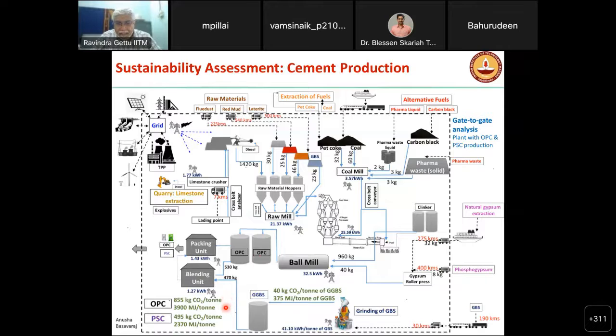It requires 3,900 megajoules per ton of cement. Now, the same cement, instead of it being OPC, was PSC, Portland slag cement, where we are using granulated blast furnace slag, ground granulated blast furnace slag, and we truck it in, grind it and mix it in. We see immediately the carbon footprint decreases a lot. We go down from 850 to about 500.